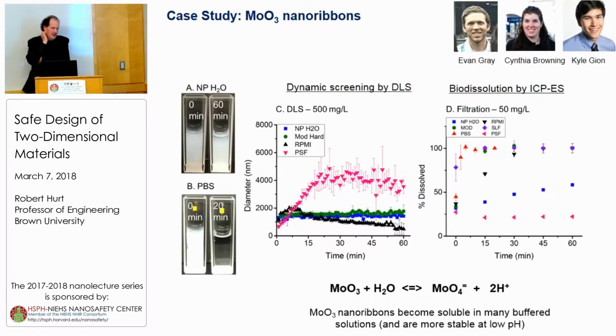And so we took a look at why this was, and of course it has to do with the basic dissolution stoichiometry. Molybdenum trioxide is hydrated by water and produces molybdate and protons. And of course, in nanopure water you produce enough protons to drop the pH, and you get an equilibrium situation where the dissolution stops, which is why Christy's stock solutions are stable. And in a lot of other media, you see stability. But in buffered media, and we always use buffered media, right? You absorb those protons, you allow this reaction to go further to the left, and you get dissolution.